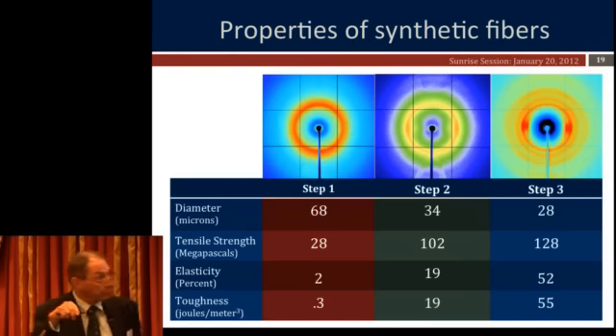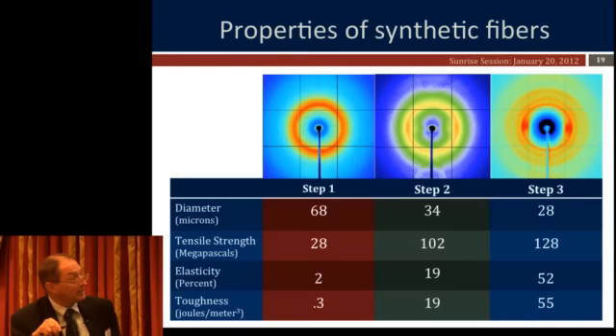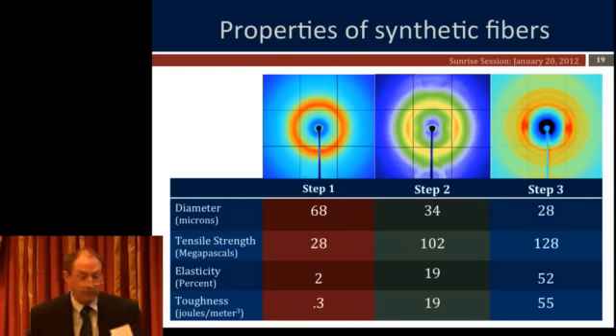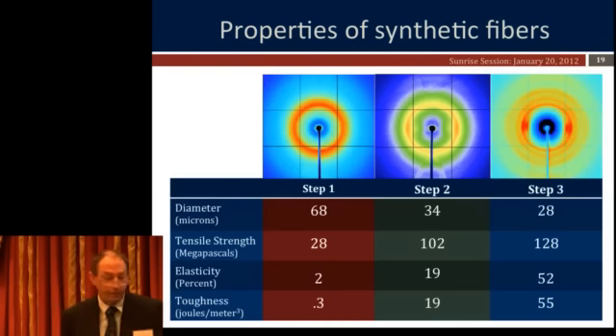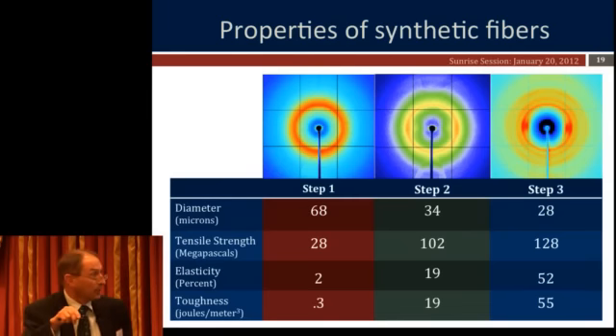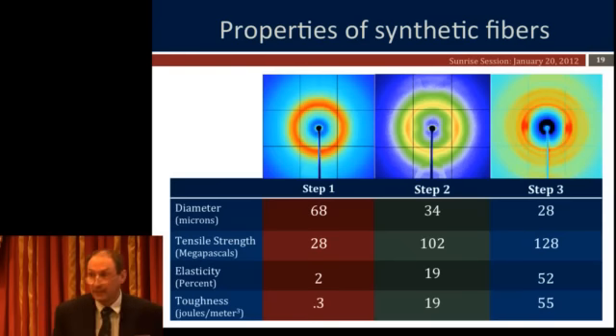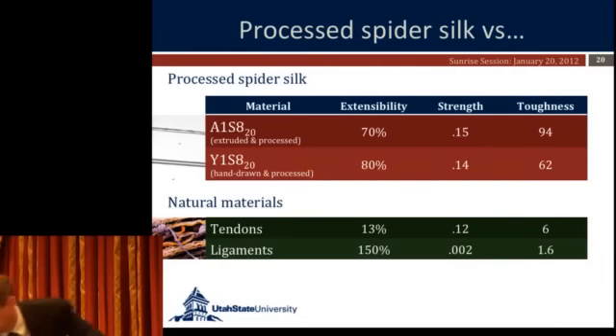And what happens is when you put it in the water, it reorganizes, and this very strong amount of X-ray diffraction right along the equator indicates that now not only have we made the Legos, but they're lined up parallel to the fiber axis, and now all of a sudden you see a much larger increase in tensile strength, a huge increase in elasticity. We're still not as good as the spider silk, but we're in very good shape in terms of the structure.